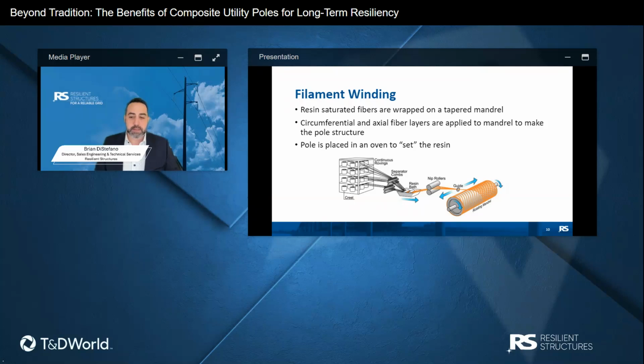Multiple alternating layers are applied to the mandrel with fibers arranged both around the circumference of the mandrel as well as along its axis. The circumferential layers enhance the hoop strength of the structure, while the axial layers contribute to its bending strength and overall stiffness of the finished pole.